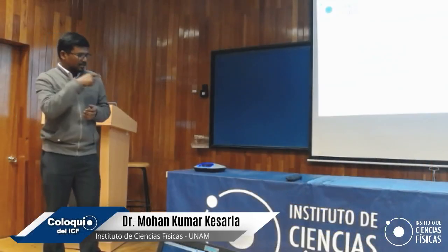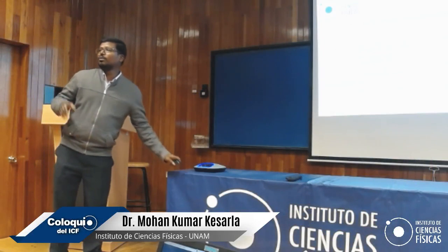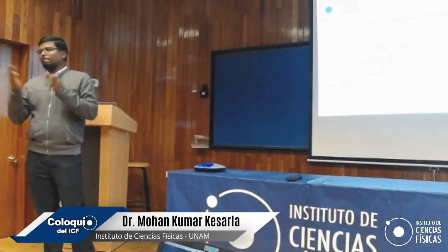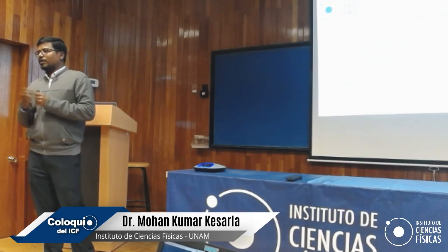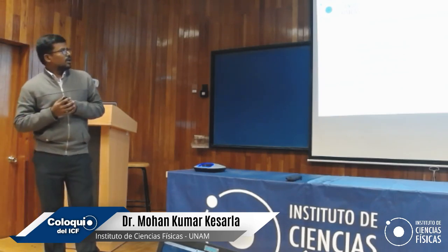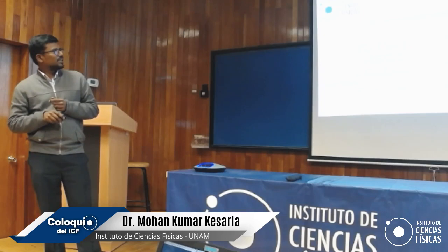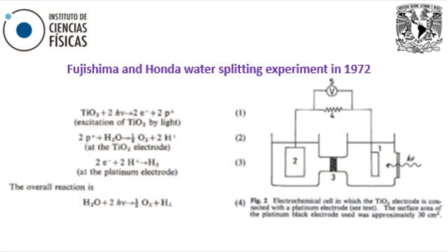But before talking about how this graphitic carbon nitride is going to give good efficiency in producing hydrogen, I will start with the work done in 1972 by Fujishima and Honda, who were the pioneers in splitting water and getting hydrogen. They prepared an electrochemical cell where one electrode was coated with titanium oxide and the other was a platinum electrode, and they exposed the titanium oxide to UV visible radiation. And then what happened?